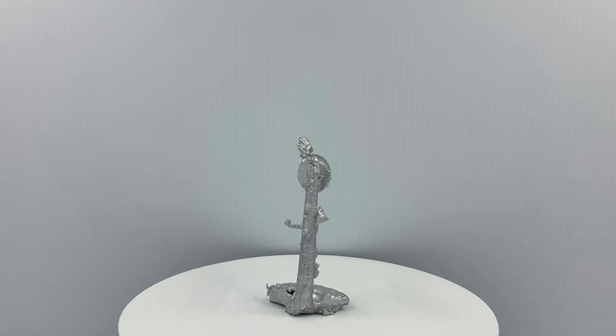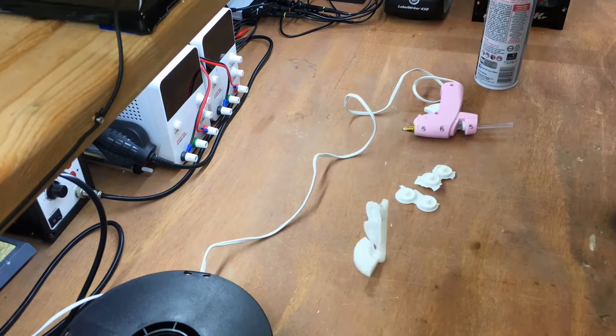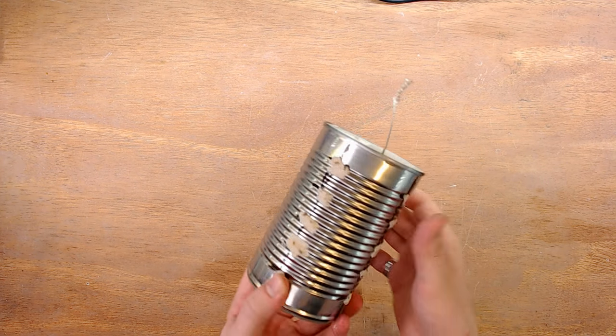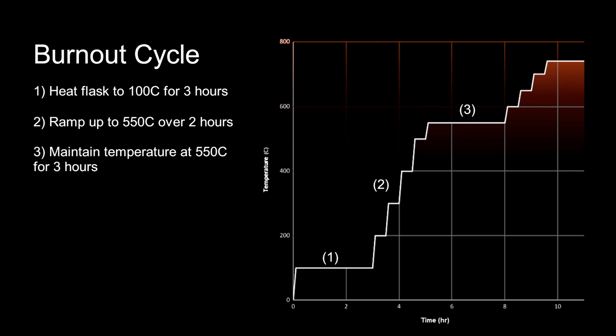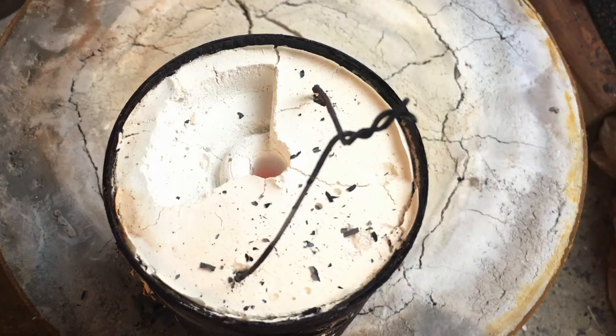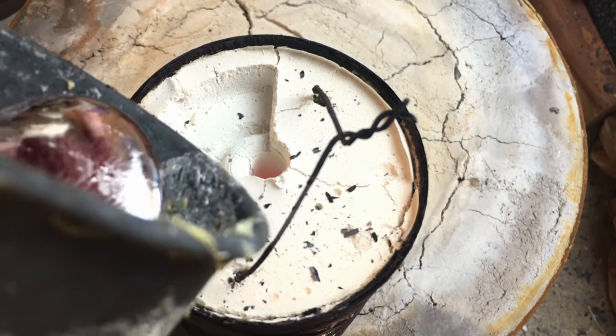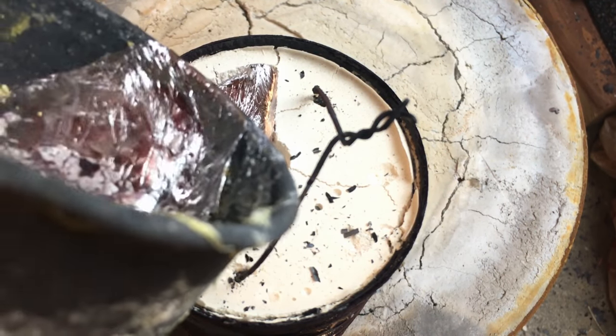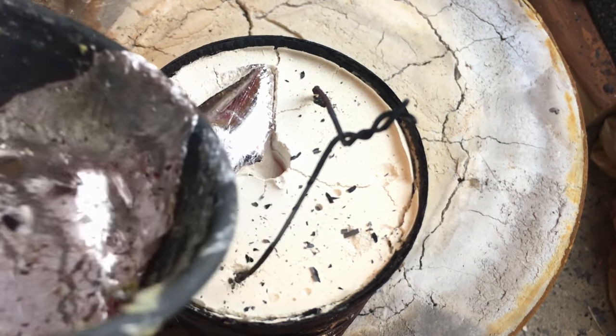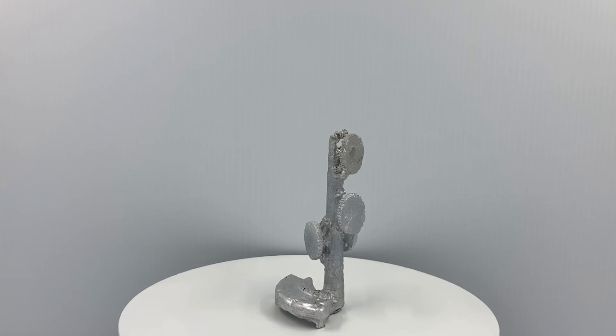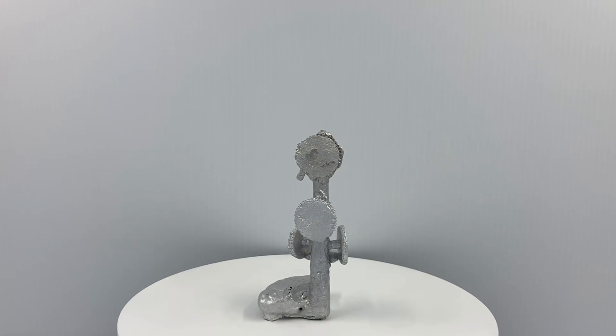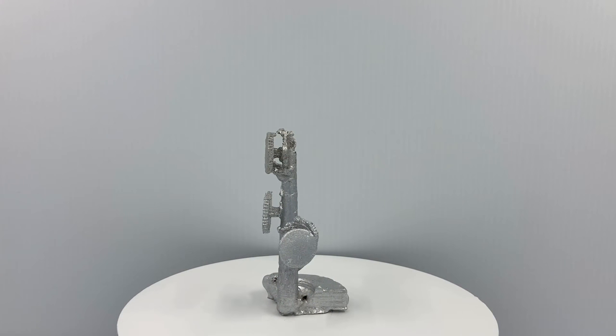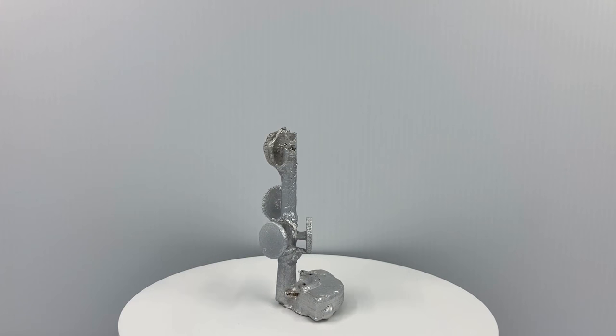So this perforated flask is supposed to be used in a vacuum machine. I don't have the money for that and I really should be getting better results with how much ventilation I have anyway. So maybe the temperature is too low. Let's make sure it's hot enough. For this next run I made the sprue a little larger so the aluminum won't cool down as quickly while it flows through the mold. I kept the plaster in the furnace for two hours at 760 degrees celsius. That's half an hour longer and 20 degrees hotter.